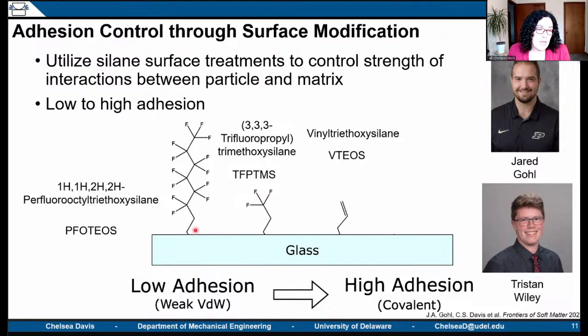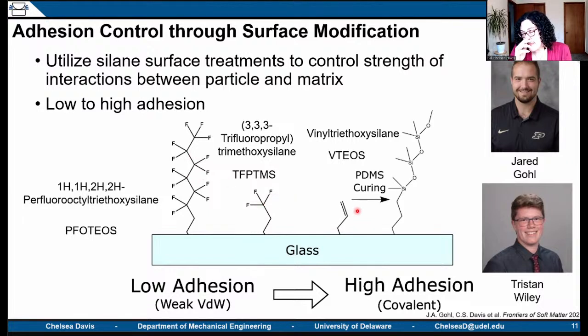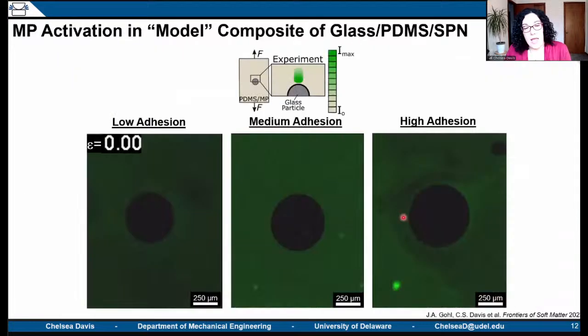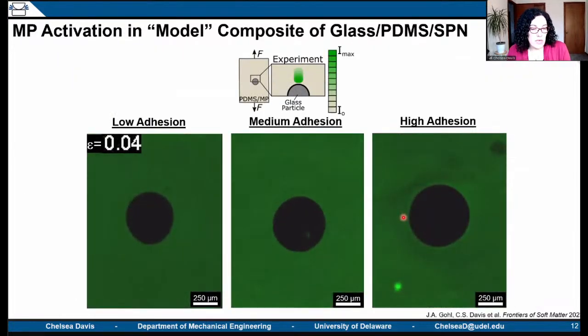And this was our attempt to get low, medium, and high adhesion, because in the case of the vinyl terminated silane, we could induce covalent attachment as we cured our PDMS matrix around the particle. And this was really successful. This was a fairly straightforward strategy that allowed us, if we look as a function of strain, I'm pulling up and down on this object.